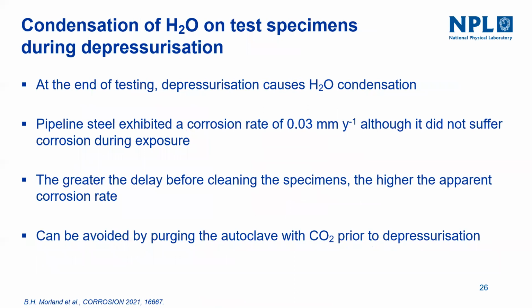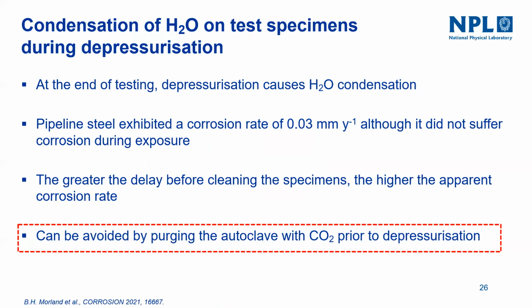So this is the condensation of the water. Normally, at the end of the testing, we depressurize the autoclave. We have seen the influence of the temperature and the pressure on the solubility of the water. Once you start to depressurize, the solubility of the water decreases, and that leads to condensation.